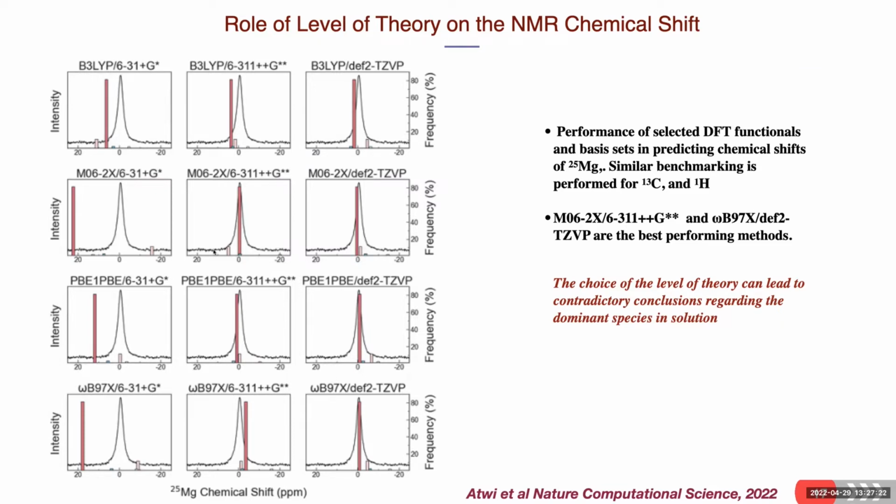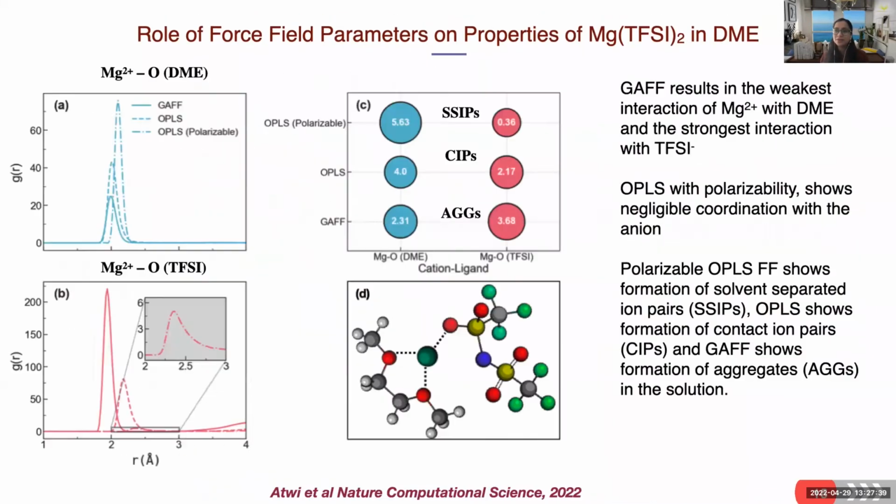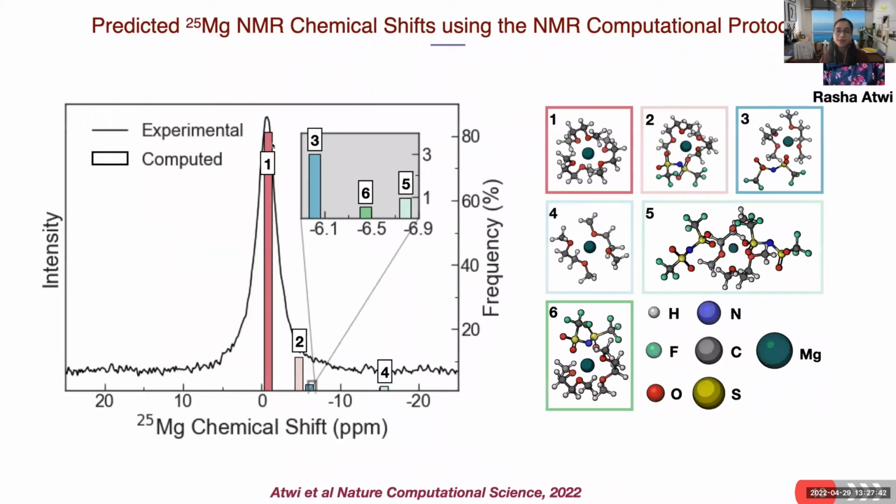And in terms of your application in mind here, how accurate is accurate enough, or were you actually asking about trends rather than absolute values? In this particular case, our accuracy was quite impressive because we found a chemical shift difference of less than 0.5 ppm, which is acceptable. Even experimental results are not that accurate. So 0.5 to 1 ppm is a really small error that we are talking about. So for these types of calculations, we found pretty good accuracy. I can't say that for every other property that we are predicting. Good, thank you.